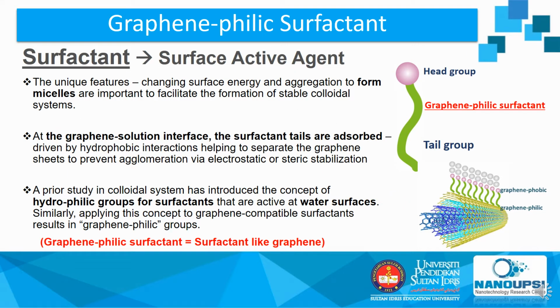As we know, surfactant is the abbreviation of surface active agent. In latex technology, at the graphene solution interface, the surfactants are adsorbed, driven by hydrophobic interaction, helping to separate the graphene sheets and prevent agglomeration through electrostatic or steric stabilization. By the colloidal science concept, if the surfactant component has favorable interactions with water, we call it hydrophilic. The same goes for graphene: if the surfactant component has favorable interaction with graphene, we can call it a graphene-philic or graphene-compatible surfactant.